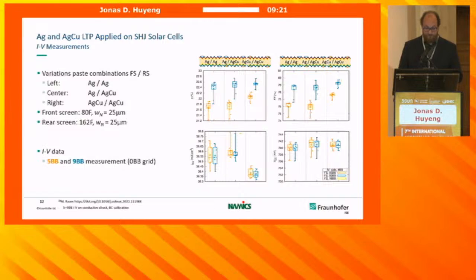The front side had 80 fingers, the rear side had 162 fingers, all printed with 25 micron opening. And then we did the IV measurement data with different busbars. So we have a 5 busbar configuration in orange, a blue 9 busbar configuration, and then we used this also to estimate a 0 busbar situation.